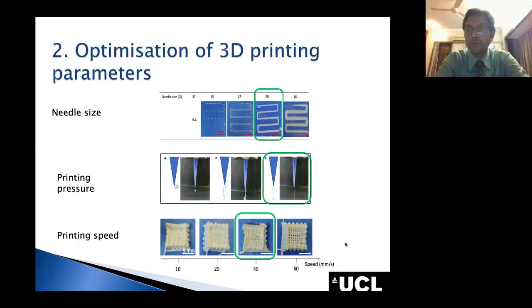Then, once we optimize the ink formulation, we move to the basic 3D printing parameters, such as the needle size, the printing pressure, and the printing speed. In this case, we used a 20 gauge needle, which is around 0.41 millimeter diameter, and the pressure was optimized visually. It didn't have to be too low or too much, just as shown in the middle picture.